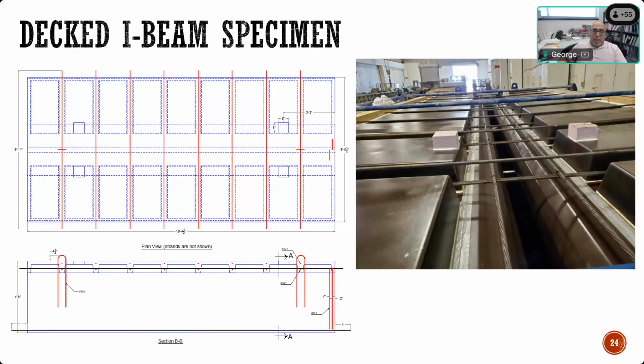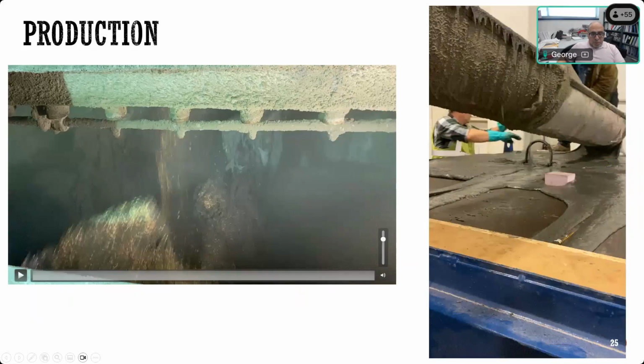Here's a picture and a drawing of the specimens we did in Nebraska before we went into this project. We did a couple of specimens to check the performance and the production of this kind of section. So that's a specimen that is 20 foot long, 10 foot wide, with a form here. You can see the pans used to create the voids, and you have the ribs between the voids, and the ribs are the only part that has reinforcement. All the rest has no reinforcement except the pre-tensioning strands. So that was done.